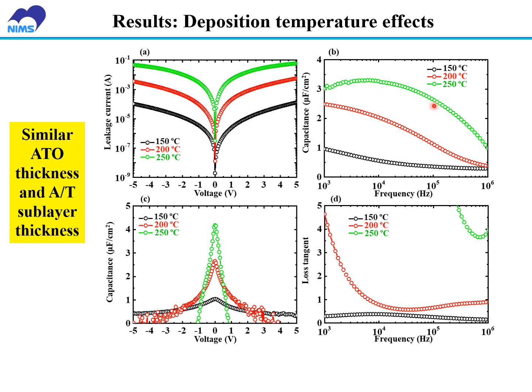The capacitance maximum for the 250 degrees C deposited nanolaminates is larger than those deposited at 150 degrees C and 200 degrees C. With the voltage change from 0 to 5 volts or 0 to minus 5 volts, the capacitance maximum decreased greatly. The loss tangent for the 150 degrees C deposited nanolaminate-based capacitor is much lower than those deposited at 200 degrees C and 250 degrees C.